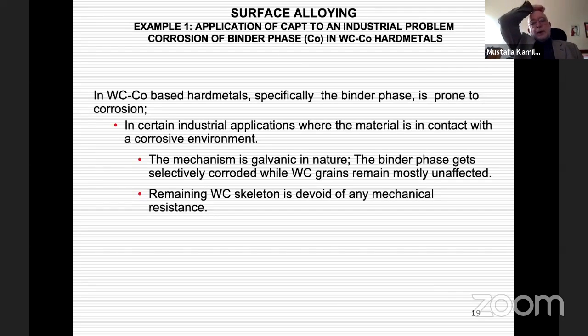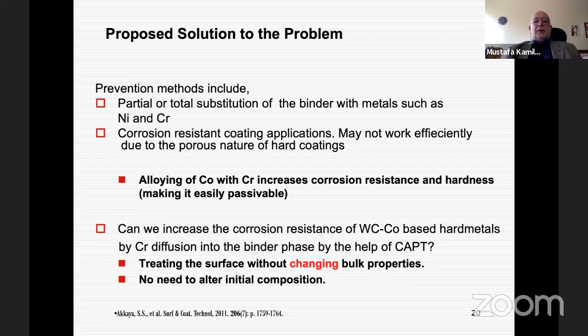This is a very well-known problem in tungsten carbide cobalt hard metals. These materials, as you know, have cobalt as the binder phase for the tungsten carbide structures. So when you use these in certain corrosive applications, the cobalt leaches away, leaving behind the tungsten carbide skeleton. So this really creates problems for their usage in such corrosive environments. So what do people do to overcome this problem? They change the composition of the binder. They alloy the binder with nickel and chromium to increase its corrosion resistance.